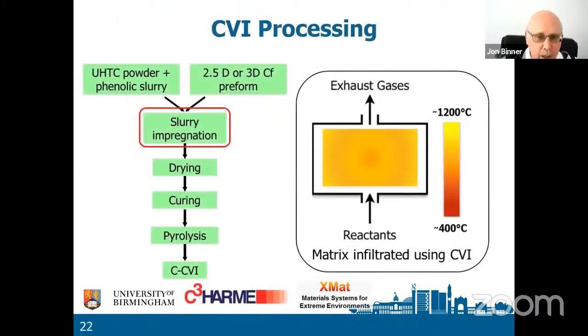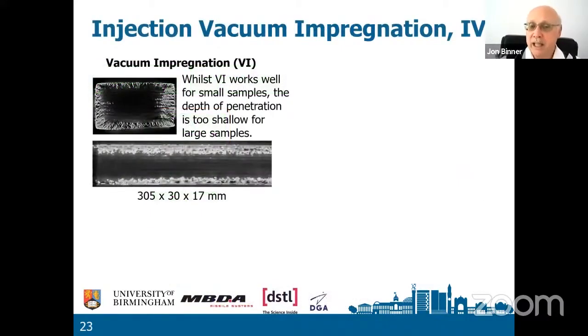Okay, it's CVI processing again. You've already seen this. And so we're going to infiltrate the matrix using chemical vapor infiltration. So we start off with a powder, ultra high temperature ceramic powder, and it's actually in a slurry made of phenolic resin. We have a 2.5D or a 3D preform. We impregnate the slurry, we dry, we cure, we pyrolyze, and then we deposit carbon with CVI. So our matrix will actually be carbon. But let's just have a little look at the slurry impregnation stage. This is something that we developed at the University of Birmingham.